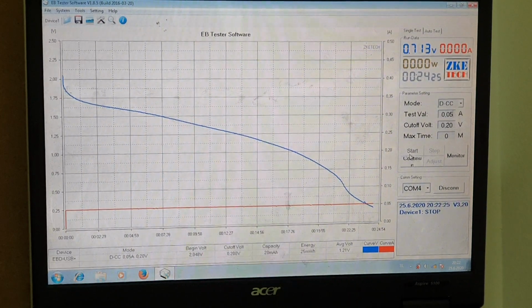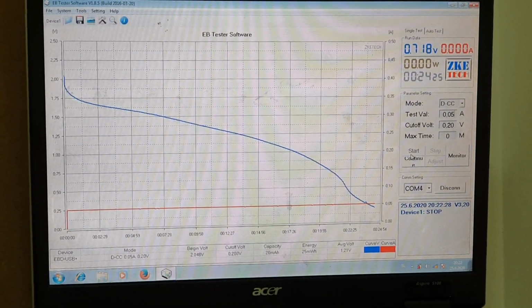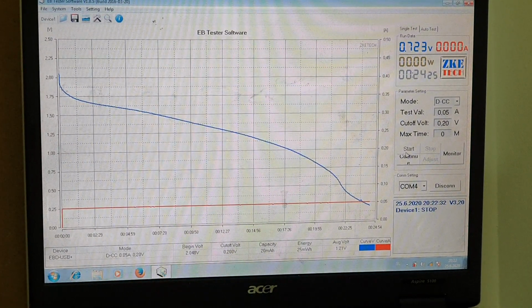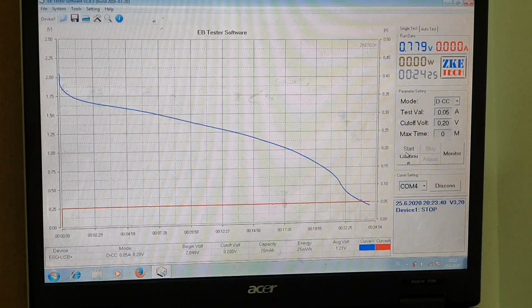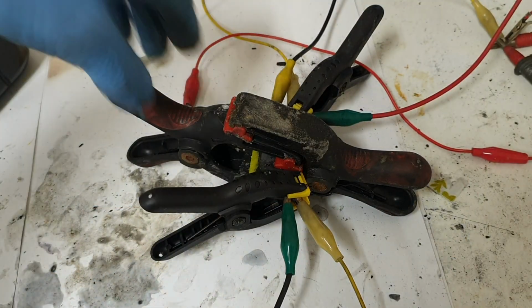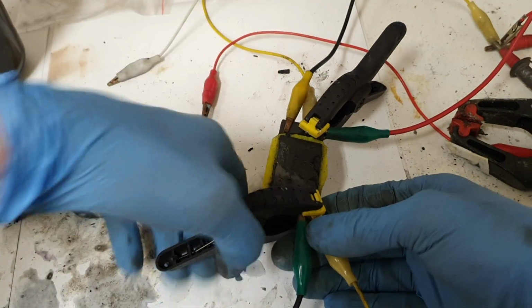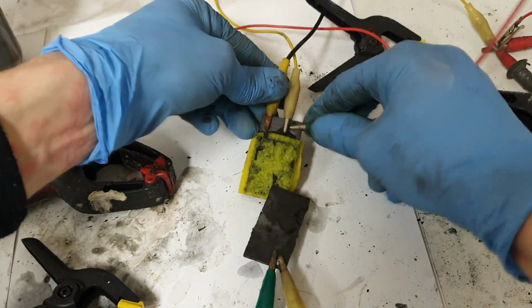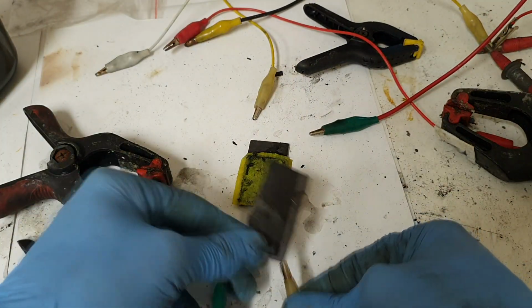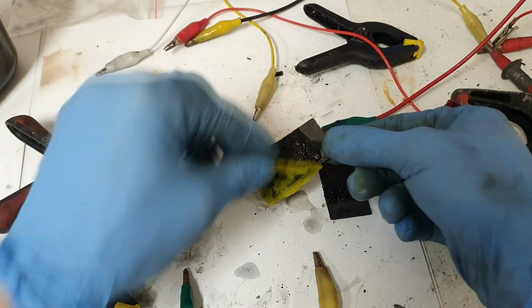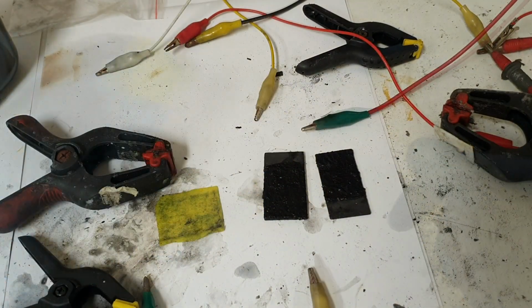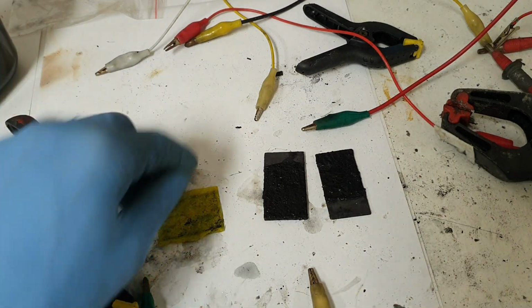So the supercapacitor is empty and right now I get the energy of 25 milliwatt hours and the runtime was 24 minutes on a 50 milliamp load, which is basically not bad. But you need to note that in the first couple of cycles the supercapacitor will form itself, so with each cycle you will get better capacity. And actually the supercapacitor is really, really simple to make. So basically that's it on this one.